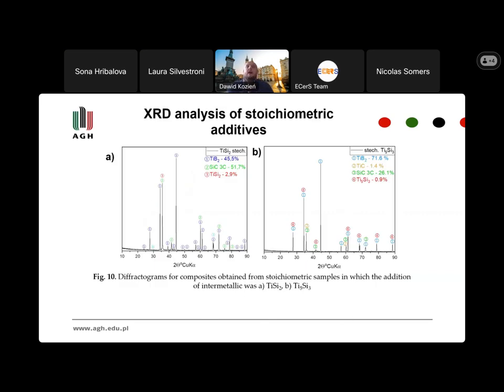And now to compare: after the sintering, we obtain completely different composites. When we use titanium disilicide, we have only titanium diboride with silicon carbide and a residual of the intermetallic. And when we use Ti5Si3, we obtain a composite with titanium diboride, titanium carbide, silicon carbide, and less than 1% of the intermetallic. So you can see how we can assume the phase composition of our composite before the sintering, and how we change the synthesis temperature. Typically, boron carbide sintering starts close to 1700 degrees Celsius. Now we can lower the temperature with different methods and different additives of intermetallic.